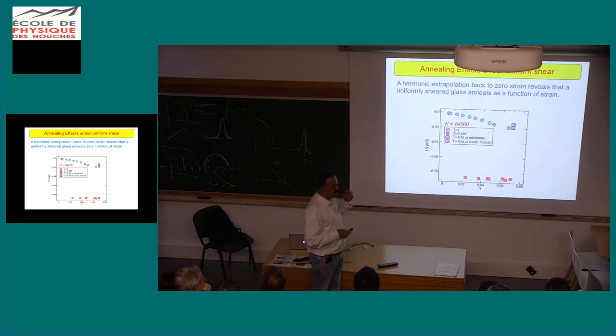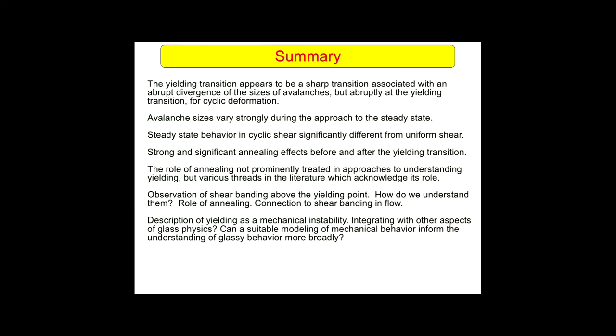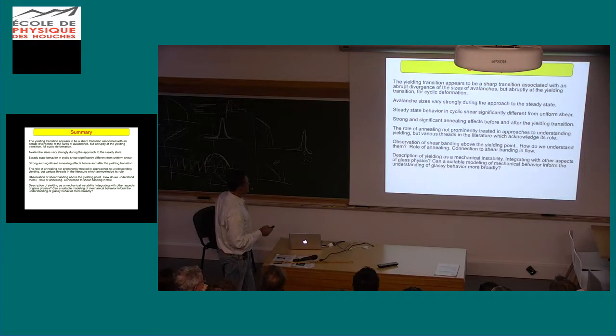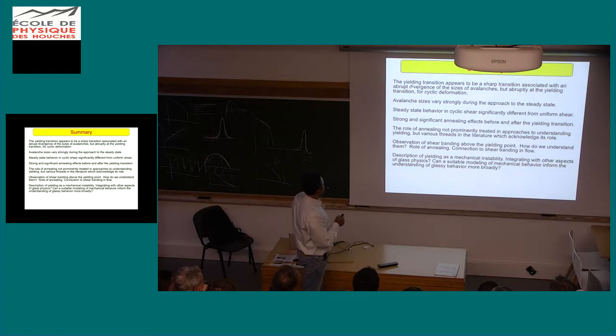Whether this is always the case and how much of a role it plays in whatever phenomenology one discusses is up for debate. So here's my summary. The yielding transition appears to be a sharp transition associated with abrupt divergence of the sizes of avalanches, but abruptly at the yielding transition rather than approaching it. Avalanche sizes vary strongly during the approach to the steady state. The steady state behavior in cyclic shear is significantly different from uniform shear. Strong and significant annealing effects before and after the yielding transition, etc. So let me stop there.